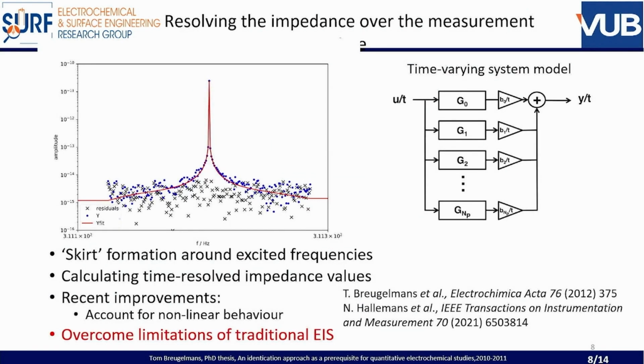Now, the next step that we are looking at is that we also have access to the non-stationarities. And this is usually forming a kind of skirt around your frequencies. It's quite complicated, but out of that, we can actually calculate the operando impedance. So in other words, if we measure the impedance over time, we can recalculate the impedance as a function of time. And this is to overcome the limitations of the traditional impedance.